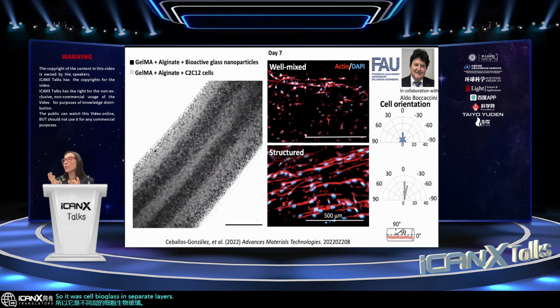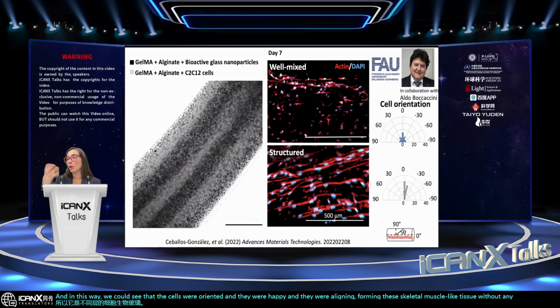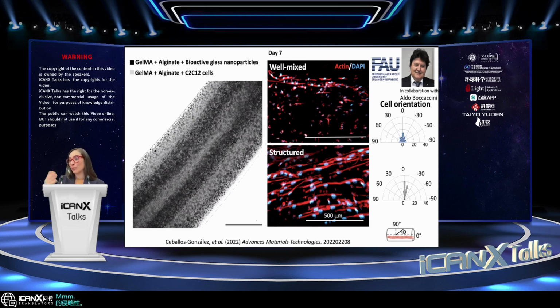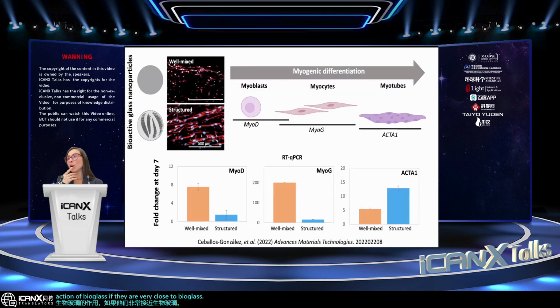And in this way, we could see that the cells were oriented, and they were happy, and they were aligning, forming this skeletal muscle-like tissue without any side effect of the aggressive action of bioglass that you would get if they were very close to bioglass. So again, we saw the expression of the markers that we expected to see over time, and this was a successful way of printing myoblasts with, in this case, a nanoparticle bioglass and cells to make skeletal muscle-like tissues.